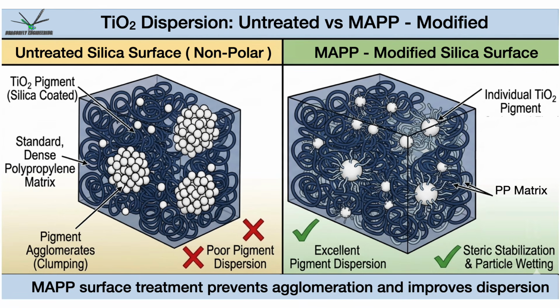This comparison outlines the major benefits for using the maleic anhydride polypropylene surface functionalization for titanium dioxide pigment particles in polypropylene matrix. The untreated silica particles agglomerate inside the matrix, resulting in poor dispersion as compared to the pigment particles that have been surface treated with maleic anhydride polypropylene. For the surface treated group on the right, the long hydrocarbon tail of the maleic anhydride polypropylene does not allow the pigment particles to get close enough to touch each other, keeping them well separated. There is good wetting and incorporation of the treated pigment into the matrix.